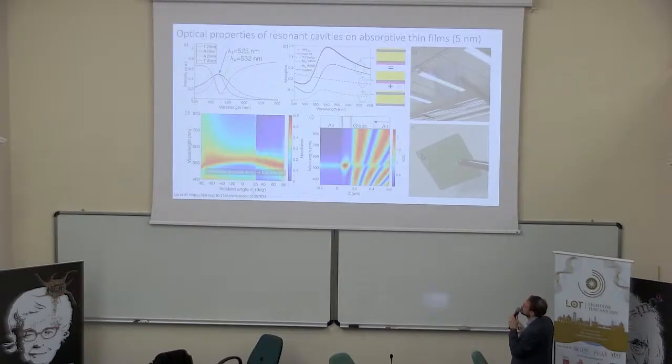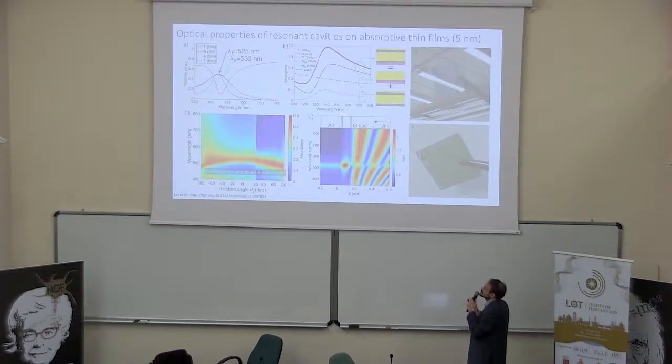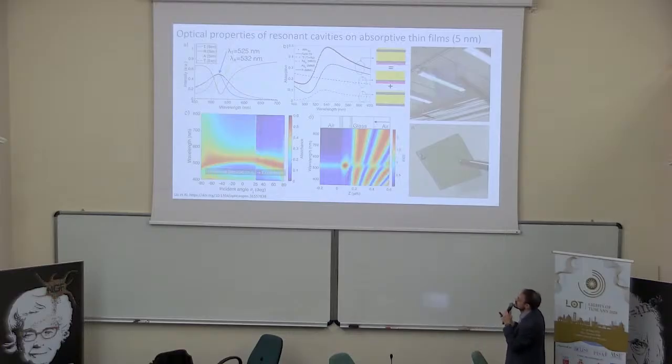When you put on the titanium that is here, the part one, and the silver, zinc oxide, then you close again with the titanium and the last zinc oxide on top, you get this particular shape. It is a resonance of a Fabry-Perot object with this thin layer. You can fit it and you can see that it is a perfect Fano resonance in this case. That presents one of the interesting features.